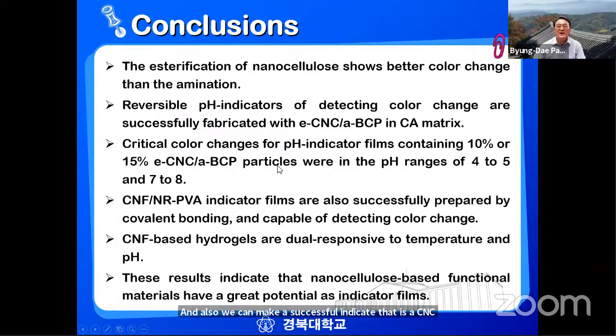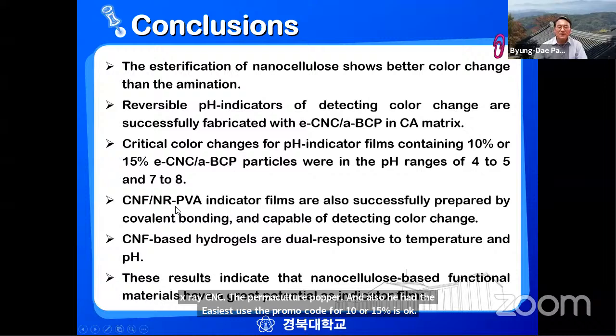So this is kind of conclusion. I would say esterification is much better color change than amination. You know, the pH indicator is detectable color changes, and also we can make a successful indicator with e-CNC and the bromocresol purple, and also we have the ECNC with the bromocresol purple. 10 or 15% is okay. And the neutral red also successful to making color change film. Also, we can detect the color change on this film.